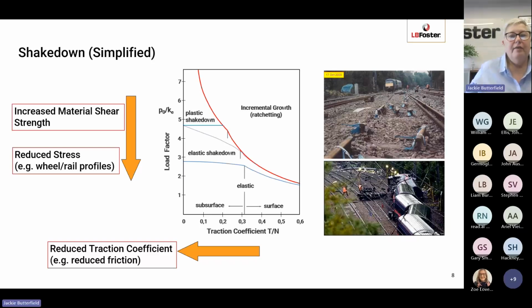So at the bottom, you have elastic behavior. So effectively, you've got reversible behavior. And then as you move up the diagram, you start to get plastic and irreversible damage behavior. But what we don't want to happen is the ratcheting effect, so this repeated cracking and crack growth. So you effectively want to stay to the left of the red line.